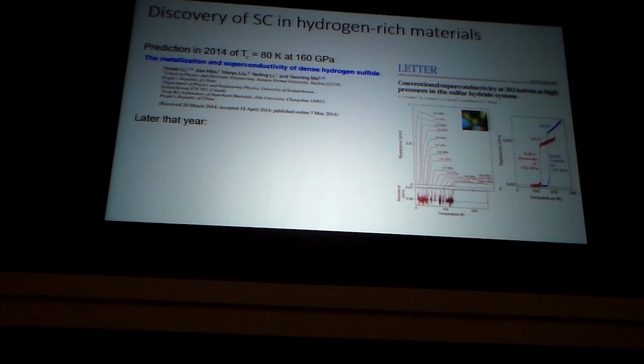Okay, so you can get high TC with the electron-phonon interaction, which I think is a big surprise to people. I think one of the main pieces of evidence that it was electron-phonon is something called the isotope effect. They substituted deuterium for the hydrogen in this sulfur hydride, so that's a different mass that's vibrating, and TC went down, as you would expect from the BCS formula. And later on, of course, they did critical field work as well, and they showed that this transition could be moved in a magnetic field, so it was indeed superconductivity.